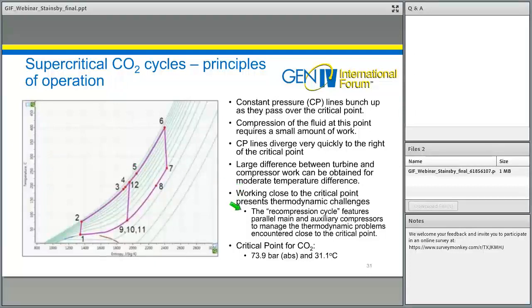The good thing about supercritical CO2 is it works very nicely on Earth. The critical point for CO2 is 73.9 bar absolute and 31.1 degrees Celsius. And 31.1 degrees Celsius complies very nicely with that minimum heat sink temperature of 30 degrees C, which I mentioned on one of the previous slides. So it works well on Earth because this point corresponds very nicely to the temperatures we can achieve with terrestrial heat sinks.